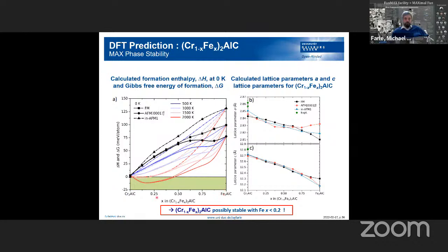So here it's pure iron, and the X stands here. Here's pure chromium, and then you add more and more iron. And that's what he finds without going into much detail. So you can calculate the lattice parameters as they change when you assume a ferromagnetic or antiferromagnetic configuration. And in the experiment, one has here 2 points, as you see. So I would say the theory is acceptable, not reaching all the ingredients which we have in the experiment.